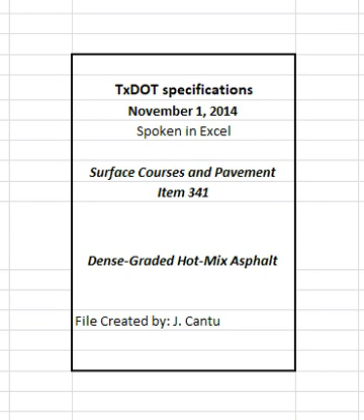4.4.2.1.14 Development of JMF2. Evaluate the trial batch test results after the engineer grants full approval of JMF1 based on results from the trial batch, determine the optimum mixture proportions, and submit as JMF2. Adjust the asphalt binder content or gradation to achieve the specified target laboratory molded density.